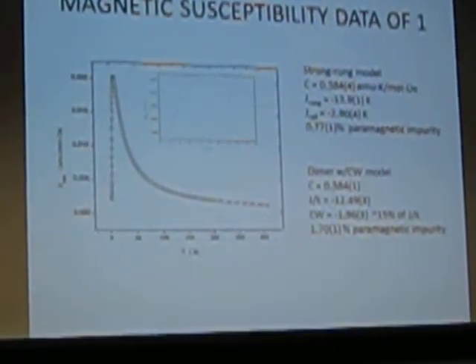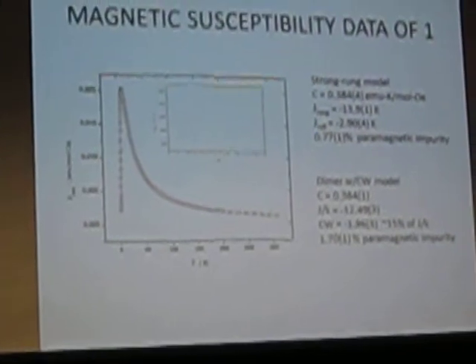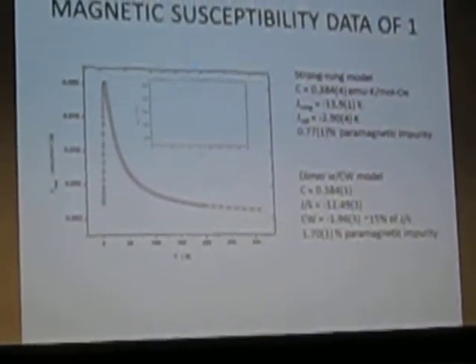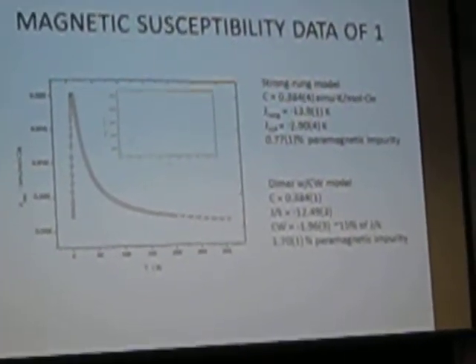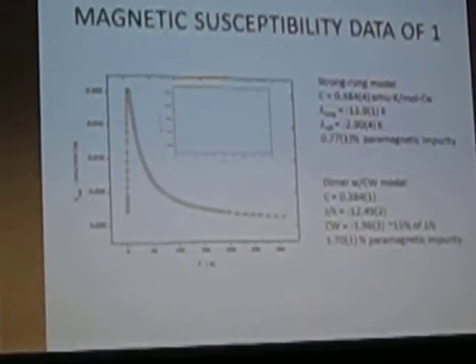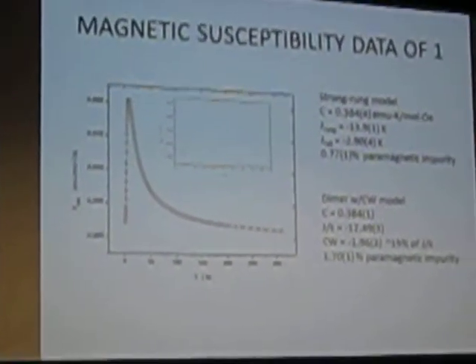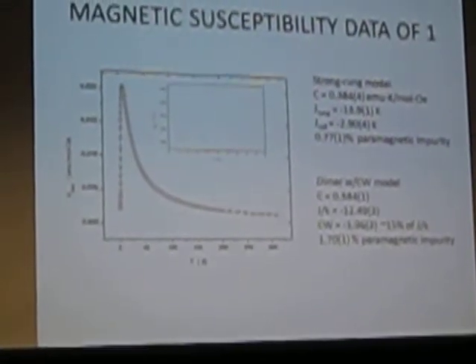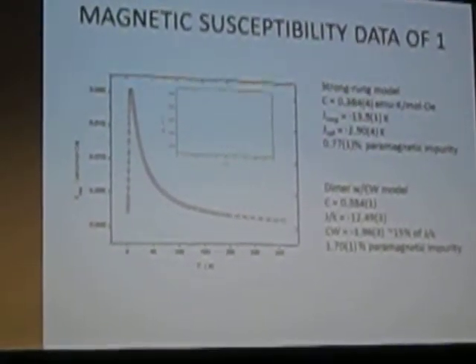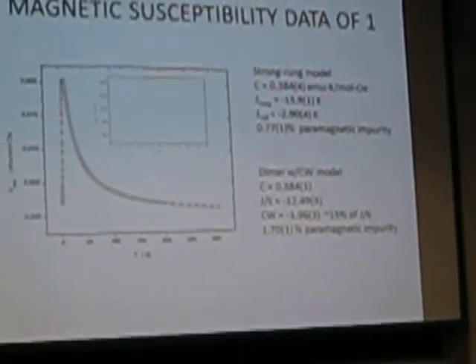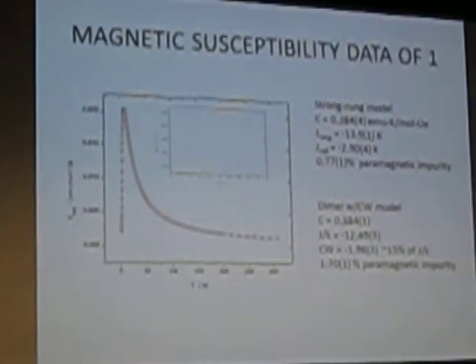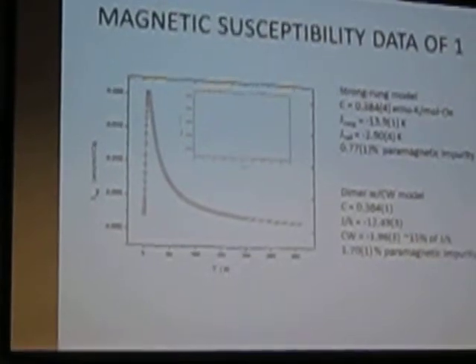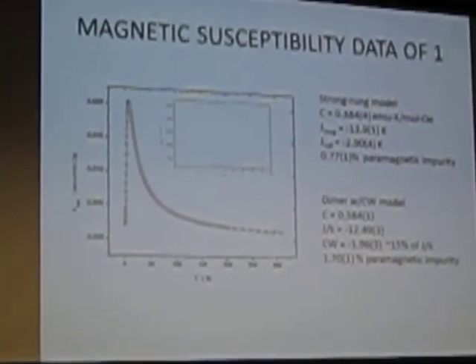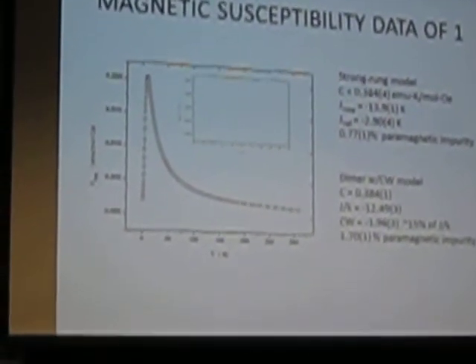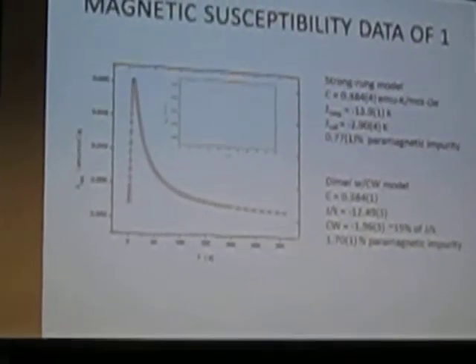But so when we do model the behavior this way, we get a Curie-Weiss constant of about 15% of the dimer interaction. So this is an invalid model, and the only valid model we can match to the data is the strong rung model. So that's about 14 Kelvin across the rung and about 3 Kelvin across the rail. So this is a strong rung. Just a little note on the magnetic impurity, that this is just an estimate, and usually the experimental paramagnetic impurity is around 2%.